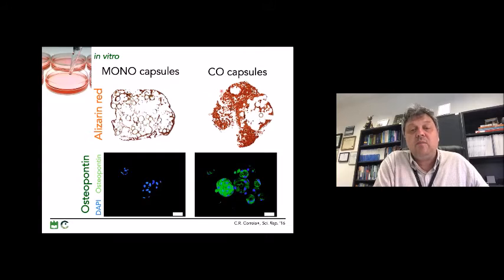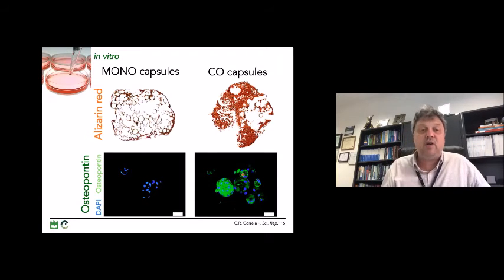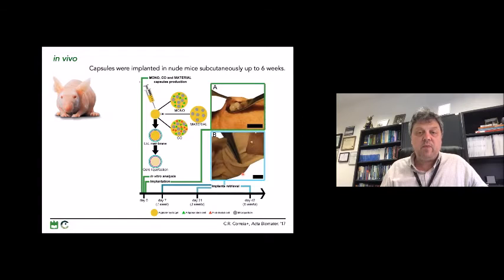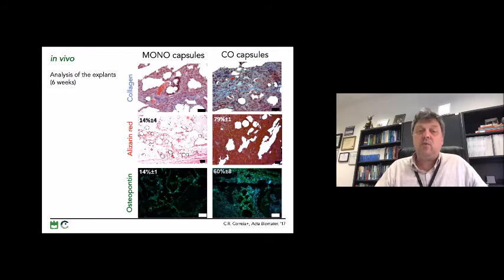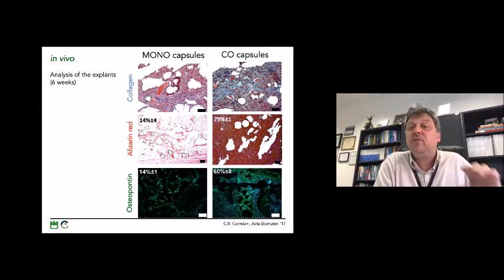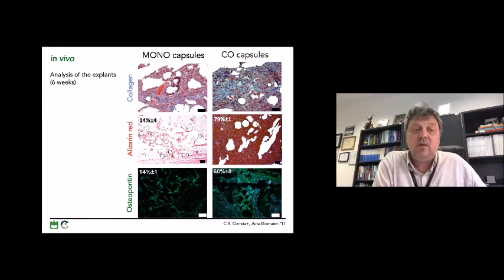However, when we culture stem cells with endothelial cells, we could see after 21 days calcium phosphate deposits that are produced inside the capsules, and we clearly detect osteopontin, therefore indicating a trend for the osteogenic differentiation. So this was in vitro. So in vivo experiments were also performed by implanting this kind of capsules subcutaneously in a nude mice model. So I will just show you one example, one slide, where we analyze the explants of the capsules that were retrieved after 6 weeks on the back of the mice.